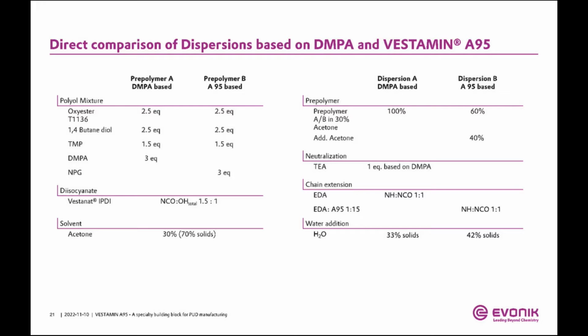The chain extension is done on the left-hand side with pure EDA. On the right-hand side, as I said, we don't need to rely purely on A95. We can also combine it with EDA or other diamines. In this case, we have a very high content of A95, so it's used 15:1 with the EDA, so almost pure A95. So even with this unoptimized approach, taking the existing dispersion A, which is DMPA based, and staying as close to this formulation as possible, just exchanging it with the A95, we are able to increase the solid content from 33% solid to 42% solid. So you increase your solid content by roughly a third already.